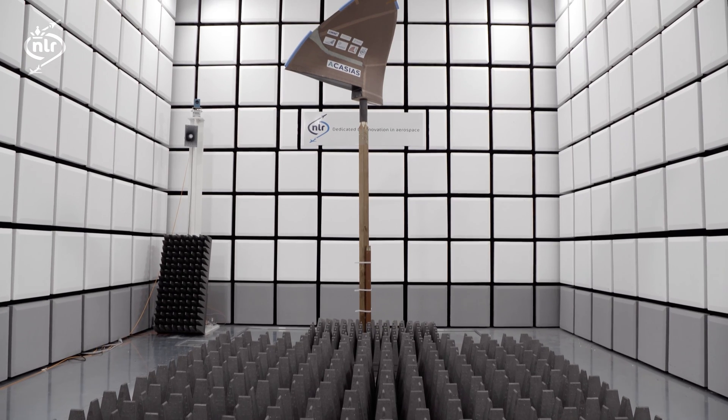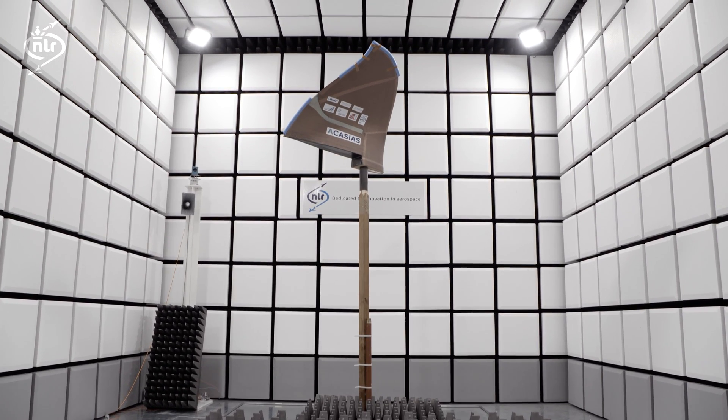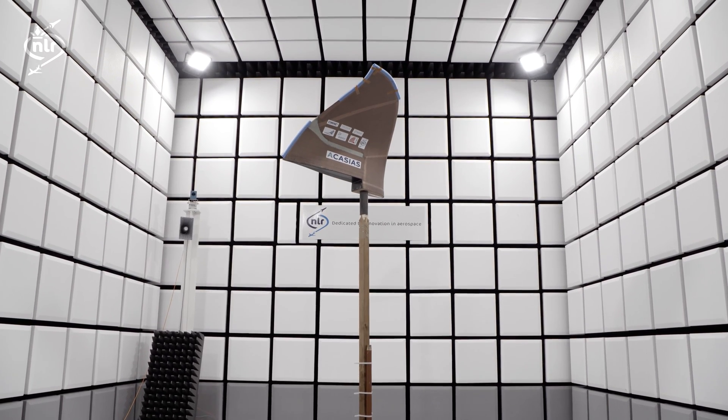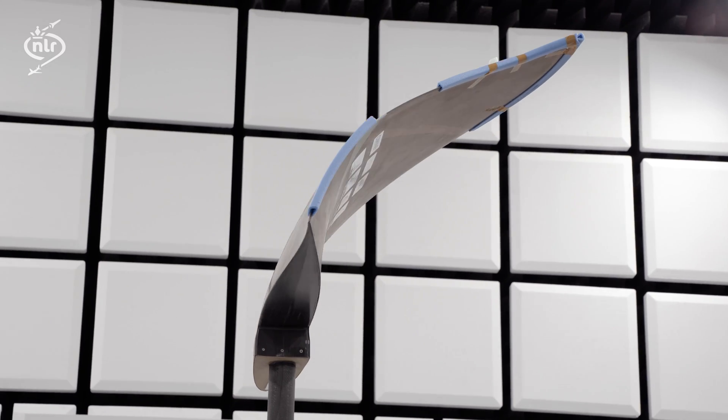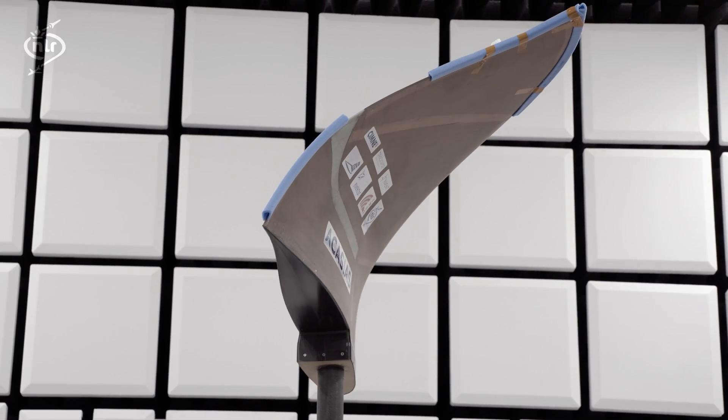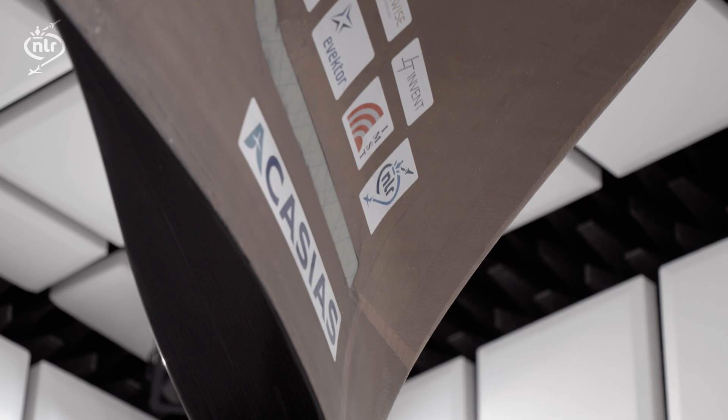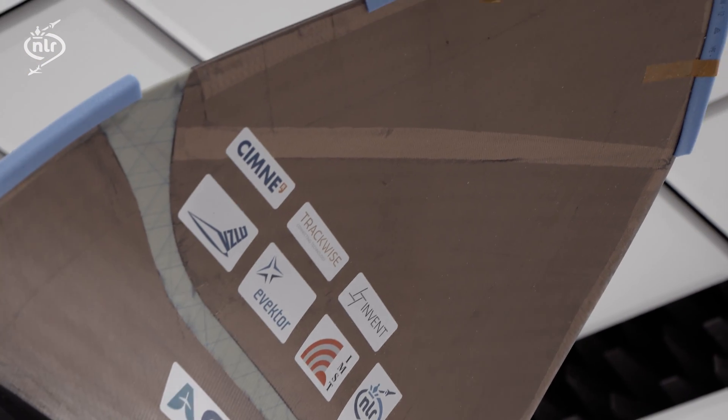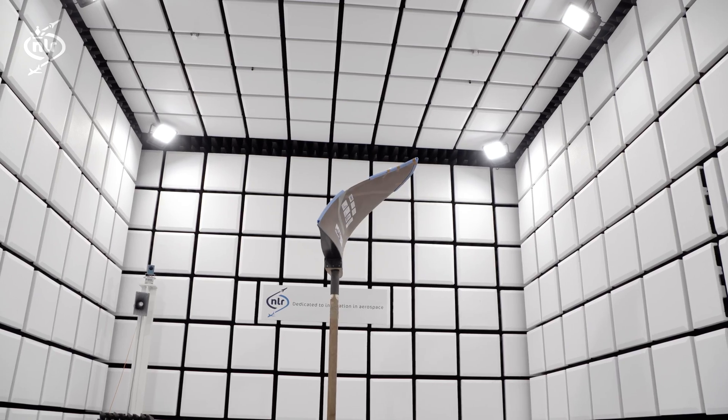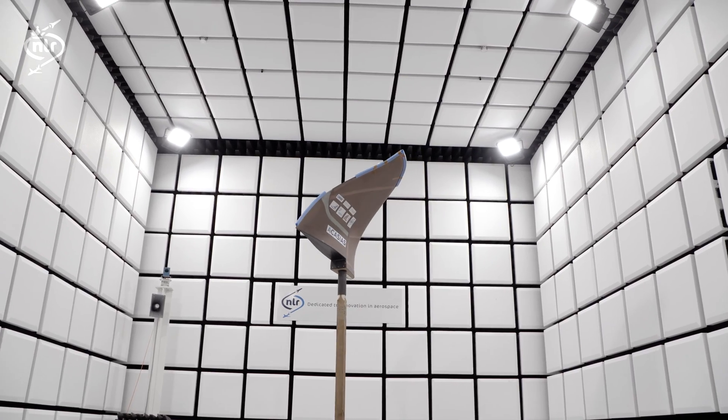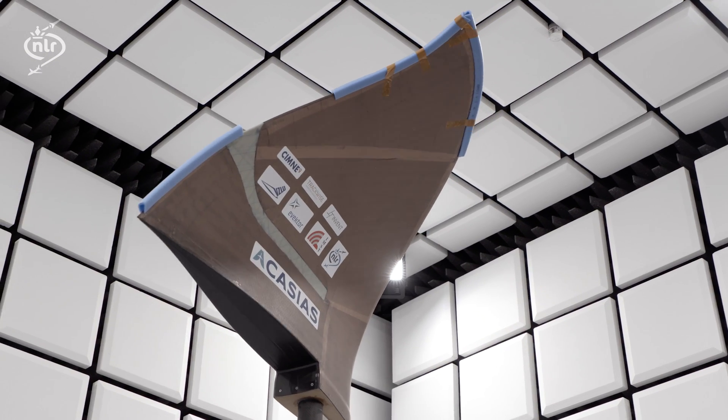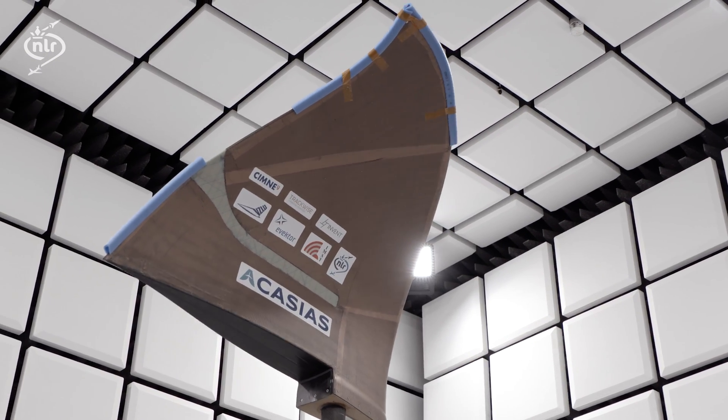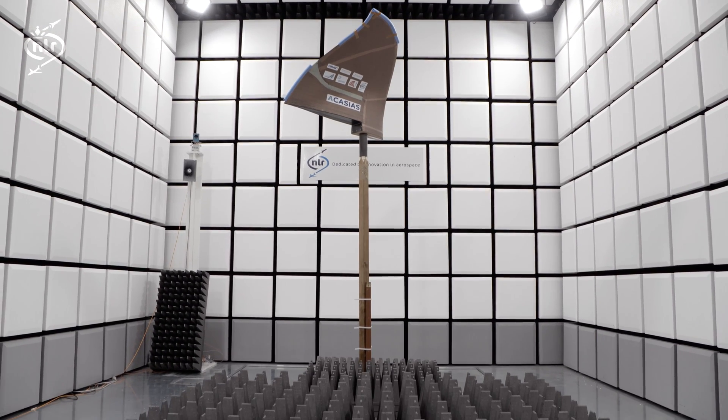The first innovative structure is a new winglet with integrated VHF communications antenna. To integrate such an antenna with its relatively large wavelengths into a winglet of a small transport aircraft is a real challenge, taking into account all the different requirements. The winglet uses carbon fiber composites and conductive material for the structural and lightning protection requirements. In the skin of the winglet, non-conductive glass fiber windows are included to enable the antenna to radiate. The antenna solution that we chose is a notch antenna that is embedded in the center of the winglet.